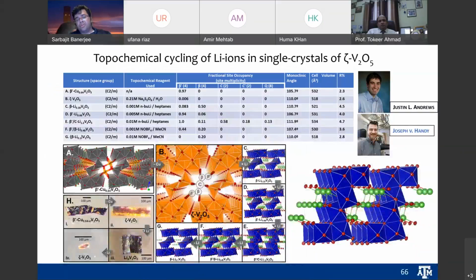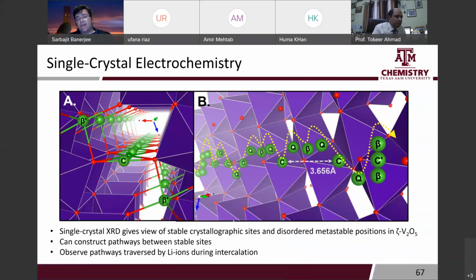So this allows us to, number one, figure out, as a function of extent of lithiation, depth of discharge, the order in which sites are occupied. In this structure, for instance, we end up filling the beta sites first, then the beta prime sites, then the C sites, and then ultimately we start filling sites that are outside of the tunnel. So this is a very powerful way of seeing exactly which sites are filled, and how the ions are moving through the lattice.